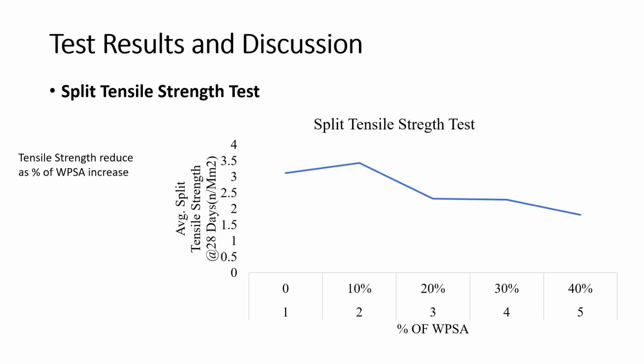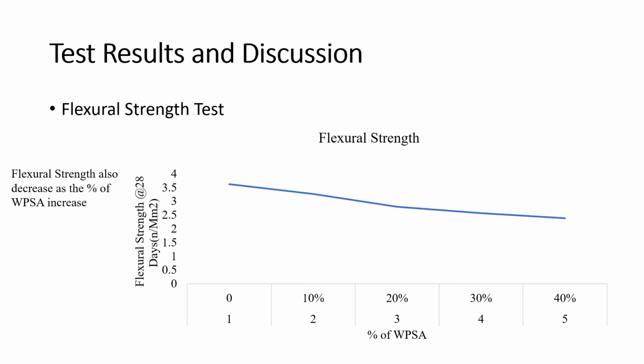The situation with the split tensile test is totally different from the compressive strength. So here from the graph, you can simply see that the tensile strength basically reduced when we increase the waste paper ash. The same thing happened with the flexural strength as well. So as we increase the waste paper ash, the strength basically reduces here as well.